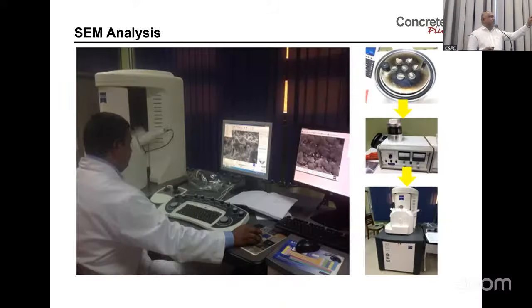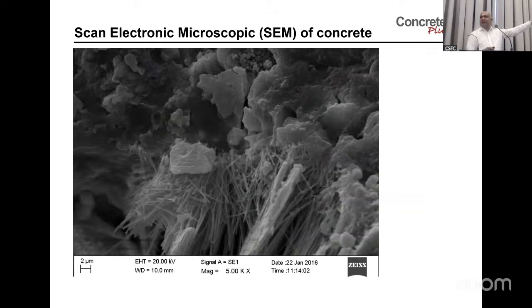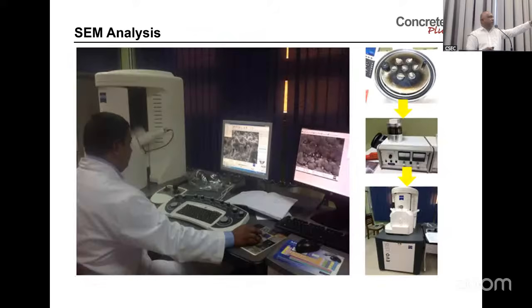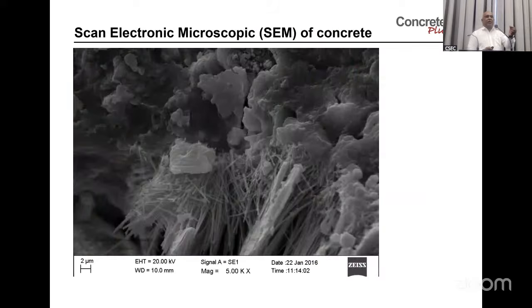This is a very small concrete particle. If you see it through the scanning electron microscope, it looks like this, like a jungle within the concrete. What you see here is a very small sample. Then you have to gold coat or carbon coat it, then put it in the machine. It's like when you check your blood to see what is inside. So this is inside concrete. You can see the magnification is 5,000. It's like a jungle. It's like an X-ray, actually better than X-ray because this is a large one. Then whoever knows about concrete can tell us what is inside, and what is going to happen. I'll show you a very good example.